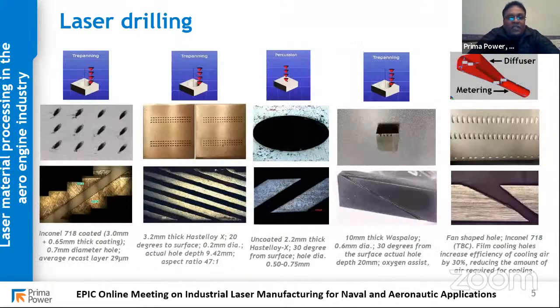With laser drilling, you can drill in different methods. One is trepanning, where you actually cut the hole out. And there's percussion drilling, where you do a single shot, which is very quick. The difference between trepanning and percussion is timing. If you have 40,000 holes to drill, it will take a long time to trepan them, so people tend to use percussion. With trepanning, you tend to get very good quality in terms of the taper and the recast layer.